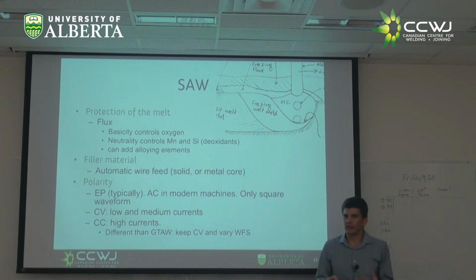So as we talked many times about welding, everything you want to do, you can. But often you don't want to do it, right? Do you want to have an awesome weld? Sure. Do you want to build a new shed and clean every weld you do? Nobody wants to do that. So in steel welding, you get away with it by having higher amounts of manganese and silicon, and that sucks up the oxide, right? But you play a funny game. For example, let's say a plate is oxidized. I weld it, first pass, right? I sucked up all the oxygen and everything. Okay. Now let's say I keep welding. Now it's clean. Now I have too much manganese and too much silicon, and my weld will be, for those of you in MATI, you know, more hardenable. So my weld is going to end up being super hard.